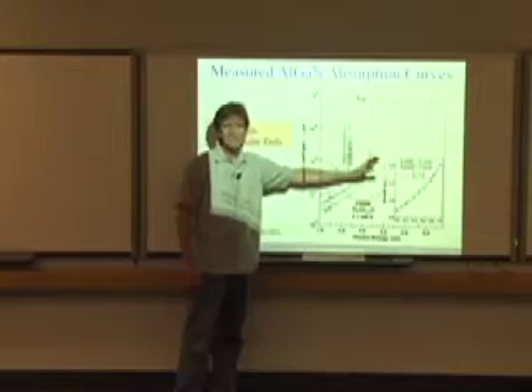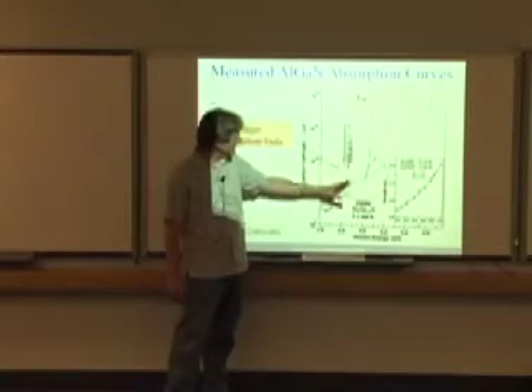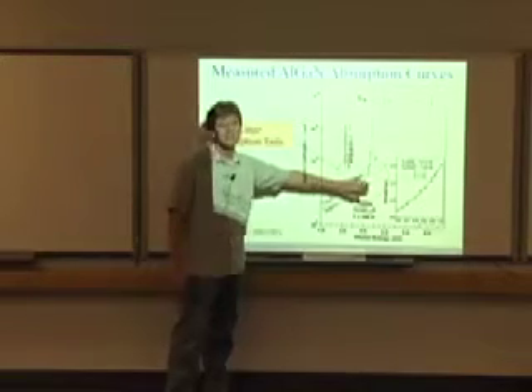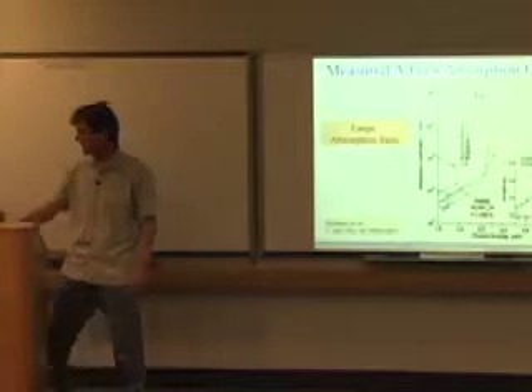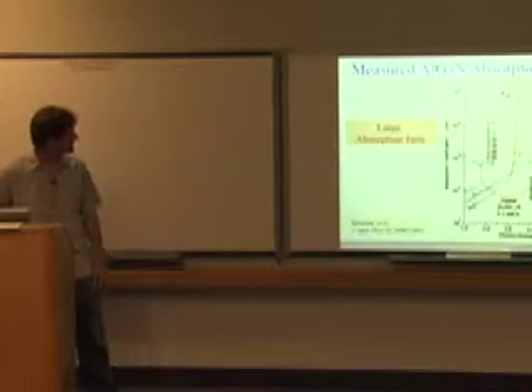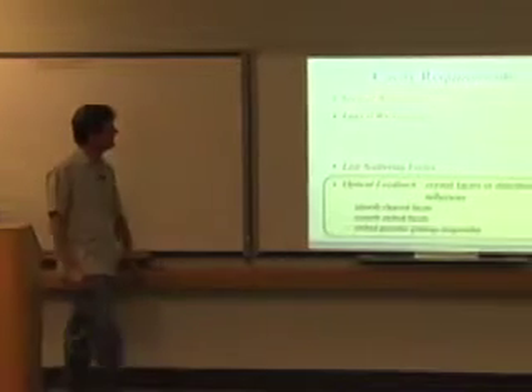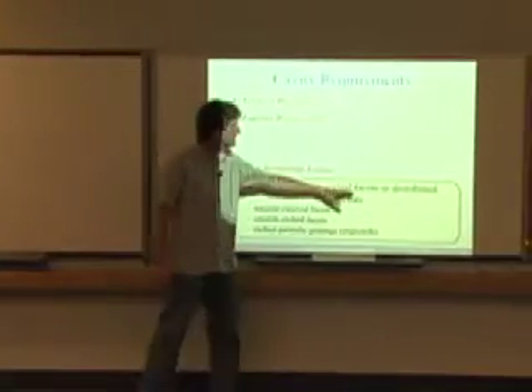Of course, I'm sure these plots vary wildly depending on the material quality, but this one particular example shows material losses in the AlGaN layer in the hundreds of inverse centimeter range. And so with this type of structure, it's going to be very difficult to make a laser because the losses are just so high. Getting good external quantum efficiency is very challenging. So then finally, for the cavity, you want to have good optical feedback. So you either have to have crystal facets or distributed reflectors.